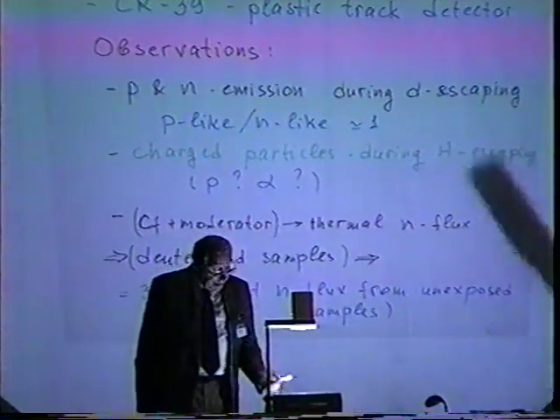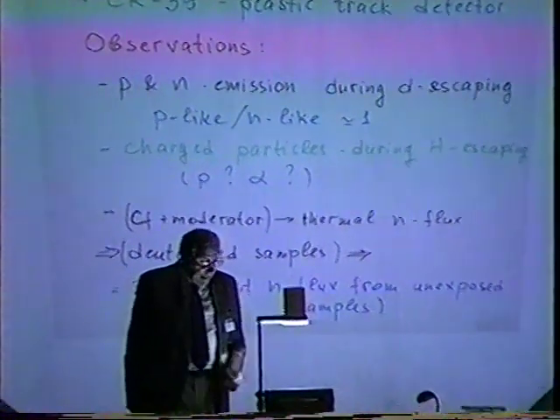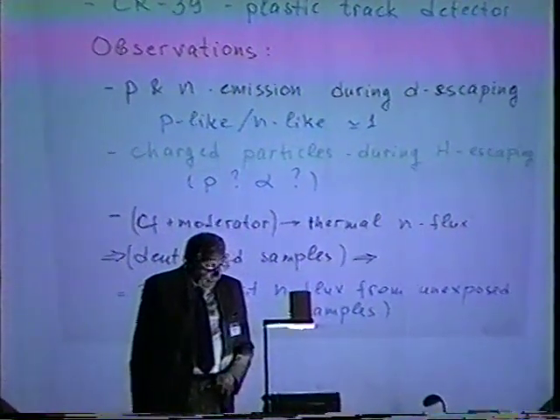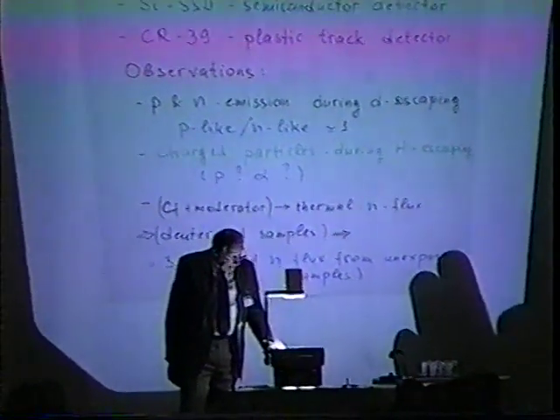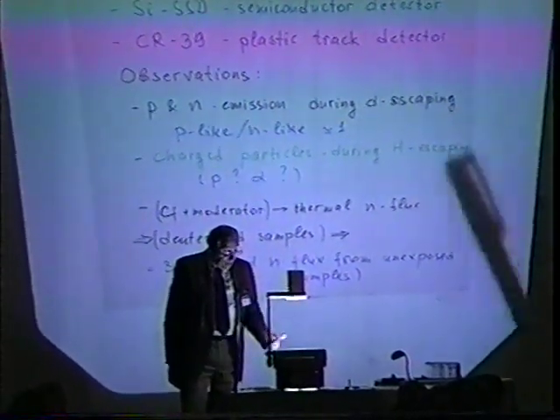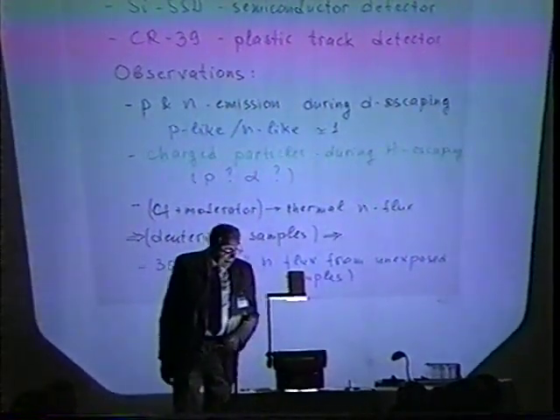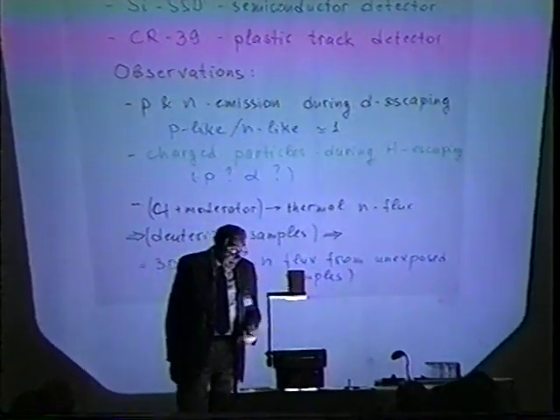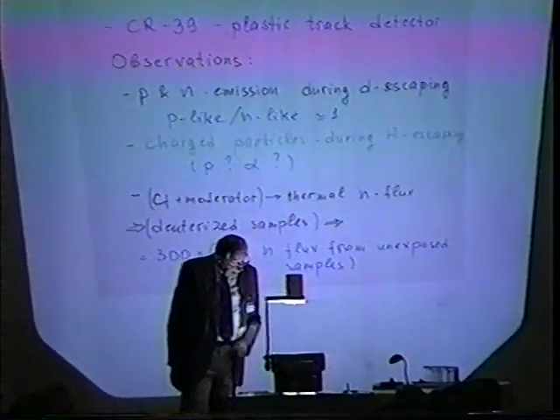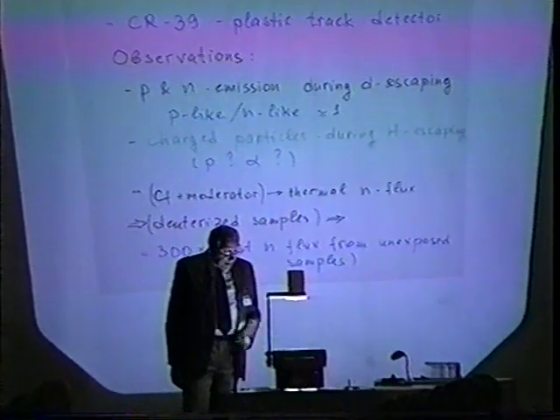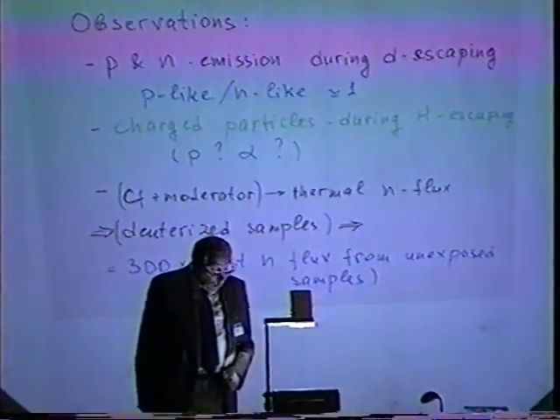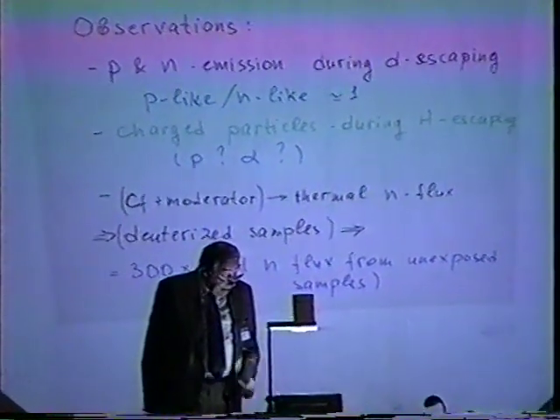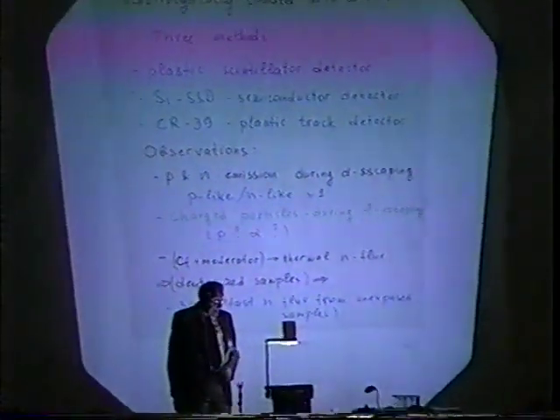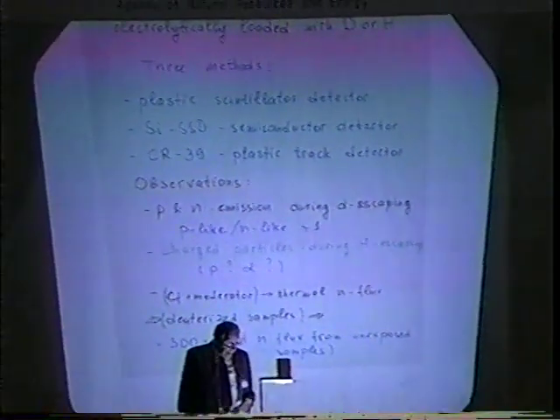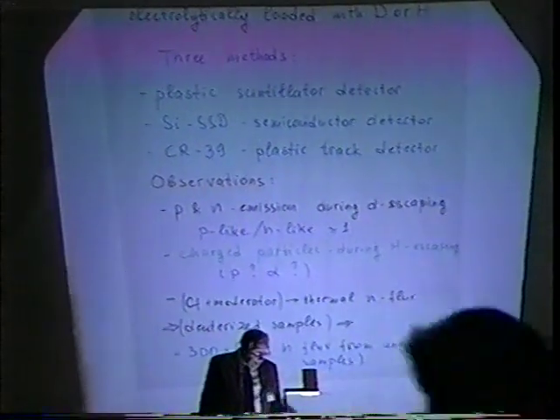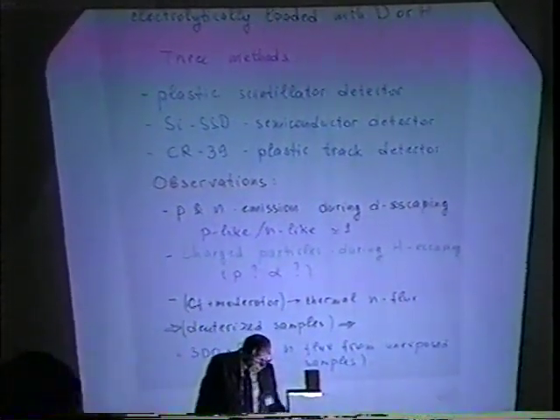What were the observations? Proton and neutron emission during escape of deuterium was observed, and the ratio of proton-like and neutron-like events was about 1. Also, some charged particles were observed during hydrogen escape, and the authors believe that probably these are protons or alpha particles. Also, irradiation of the samples by a low intensity flux of thermal neutrons was done, and it was observed that in this case the intensity of fast neutrons increased about 300 times in comparison with the same flux from an unexposed sample.